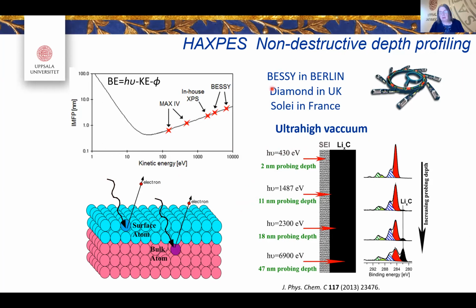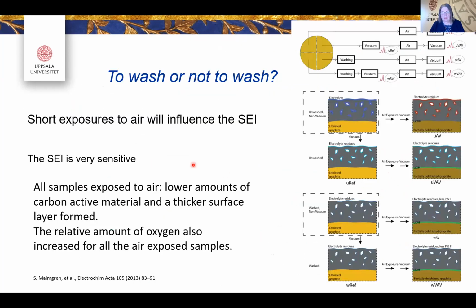We use a number of different synchrotrons in Europe. I think we can soon add also the one in Hamburg here on the list. And here's just one example of a lithiated graphite. Where you have the SEI, you can't see the lithiated graphite signal. Here you can only see the SEI components. And if you then go to higher and higher photon energies, you can actually see more and more of it. And by doing this, we can learn a lot on what's going on in this battery.